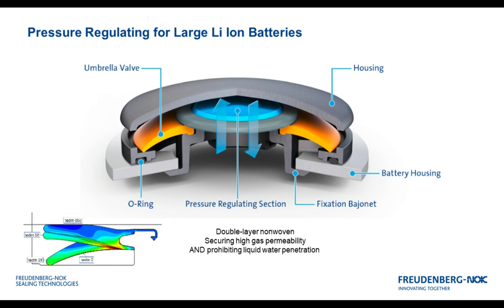And here you can see the way we accomplish this pressure regulation at Freudenberg is a technology we call the DIAVENT. And here is a picture of a cross-section of the DIAVENT, where we have those two functions of normal breathing and overpressure release accomplished within the same unit. And that first function of breathing, you can see, is accomplished by this pressure regulating section. And this is a breathable nonwoven membrane that allows gas to go in and out of the housing to regulate that pressure for your normal daily cycle of a lithium-ion battery.